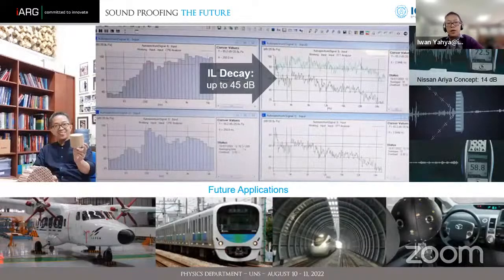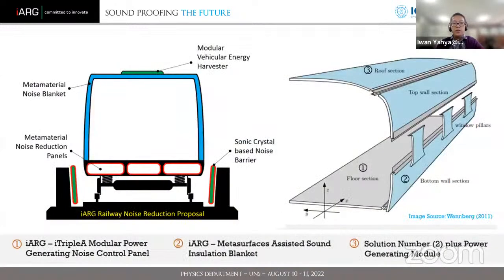You can see here, we have decay measurement, insertion loss measurement using the impedance tube. Our product's decay is up to 45 dB, while the Nissan technology is only 14 dB. So we are working with a different technology, different structure, different technique, but we also have much better performance compared to the honeycomb-based structure. So this is one of the ideas.